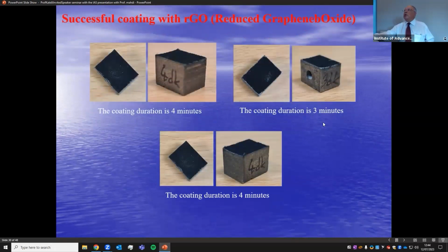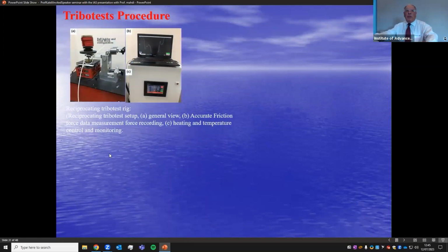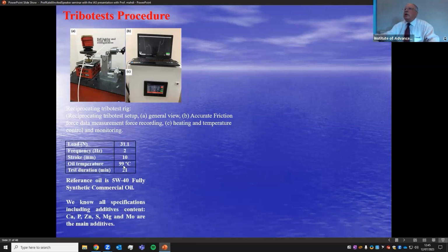Well, here you see the coating of 3 minutes, 4 minutes. And we have also 6 minutes and 2 minutes. We have more. So my tribometer is a custom-made tribometer. It's very sophisticated. It can have 800 data per second. The heating is up to, here we use the procedure, 99 degrees Celsius with 30 Newton and 21 minutes. Why 21 minutes?